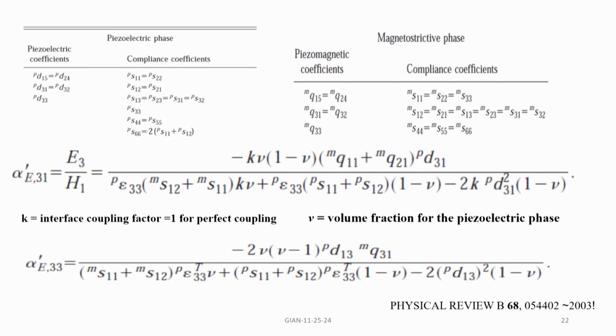So, those are the different terms. Also, S is the elastic coefficient for the piezomagnetic phase and the piezoelectric phase, and V is the amount of the two phases. If V is the volume fraction for the PZT, then 1 minus V is the volume fraction for the ferromagnetic phase.